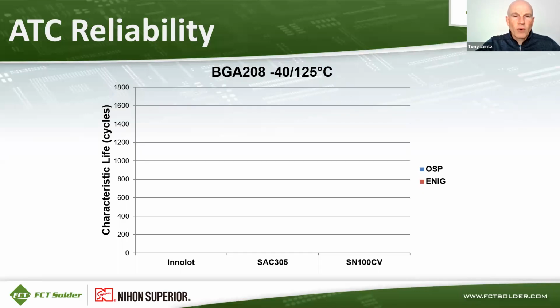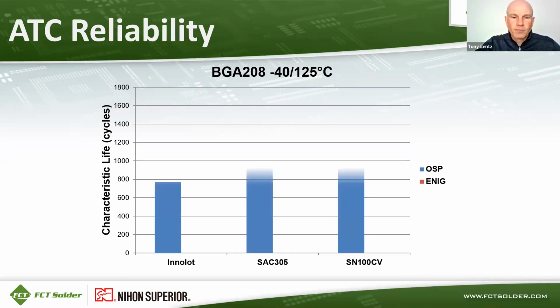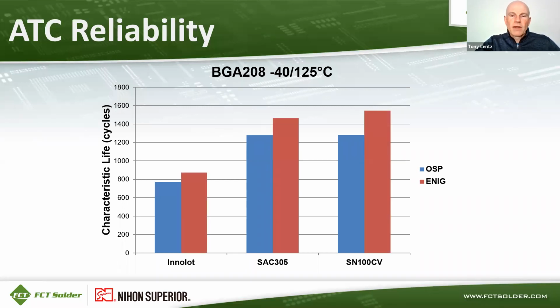Here's that same data for a BGA 208 component. Again, you've got Innolot. Innolot here, in this case, performed the worst. Innolot had the lowest characteristic life, followed by SAC305 and SN100CV, which are about the same for OSP. And then on ENIG, again, Innolot was the lowest performing alloy. SAC305 is in the middle and just a little bit lower than SN100CV on ENIG.